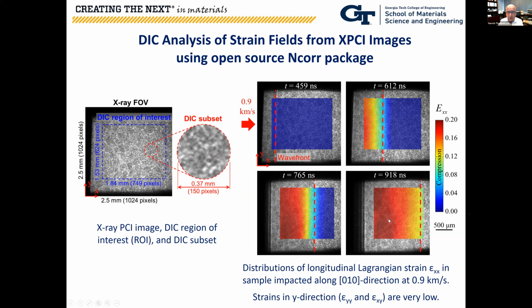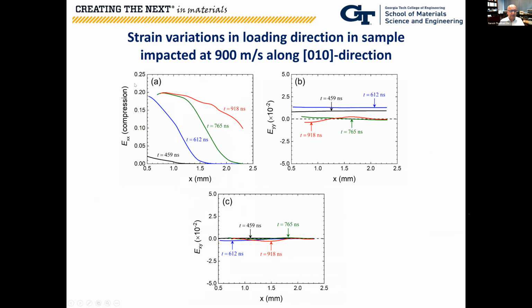In fact, if we quantify these, you can see the results here. In figure A, I'm showing you the strain variation, epsilon x component, as a function of distance at different times. As you go from 459 nanoseconds to 612 to 765 to 918 nanoseconds, you can see the maximum normal strain component epsilon xx is about 20%.